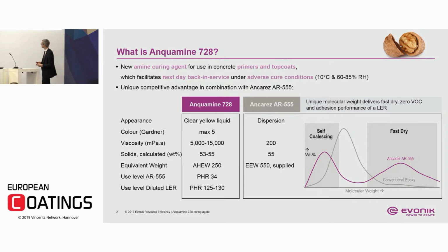The pointer's not working, but the other thing you notice is that if you look at the EEW 550 and the AHEW 250, you would think there would be a 1:2 ratio to use this product with the 555 dispersion. However, you see that our PHR at 34 is clearly lower, and that 75% stoichiometry is something we found is a very good performance point for delivering the right balance between the cure speed, the hardness properties, etc. So that's our recommendation. Don't cure this at a 1:1 stoichiometry. As typical with solid epoxy resin dispersions, you need to actually back off on the curing agent. You need to under-cure them, and then you get the best results as displayed over here.